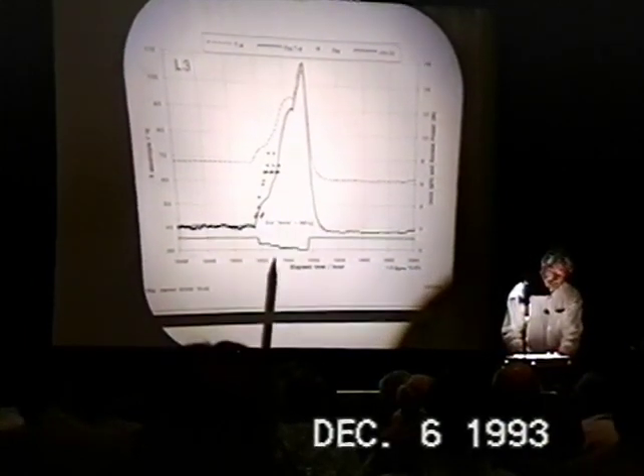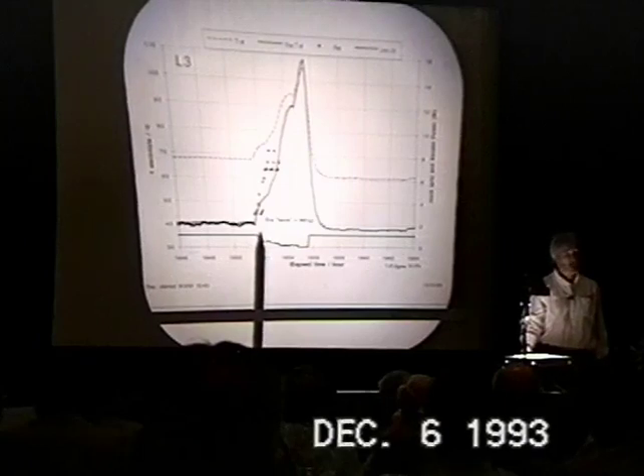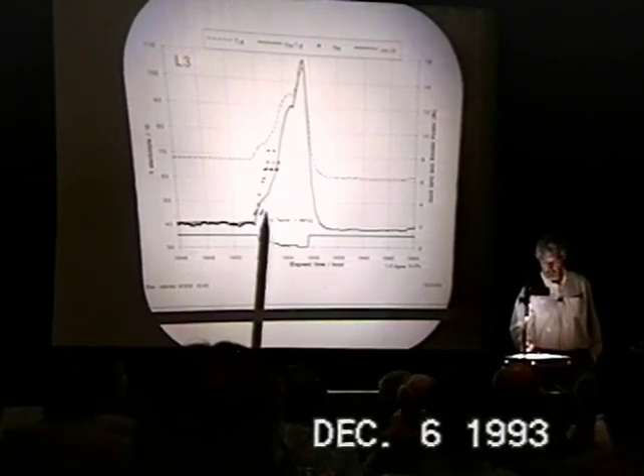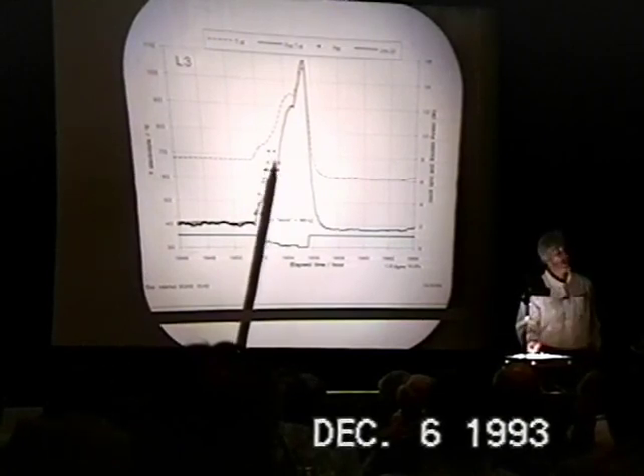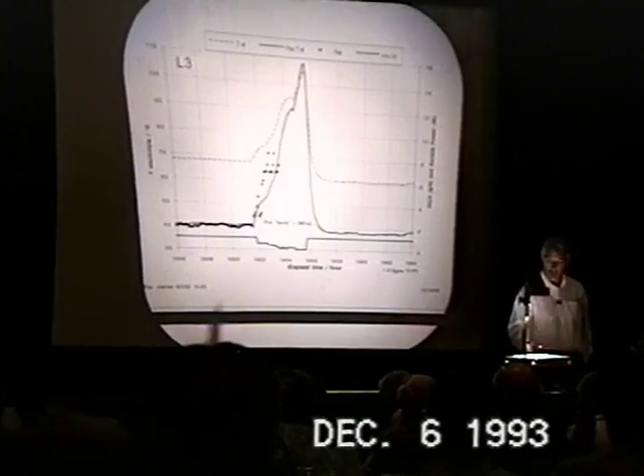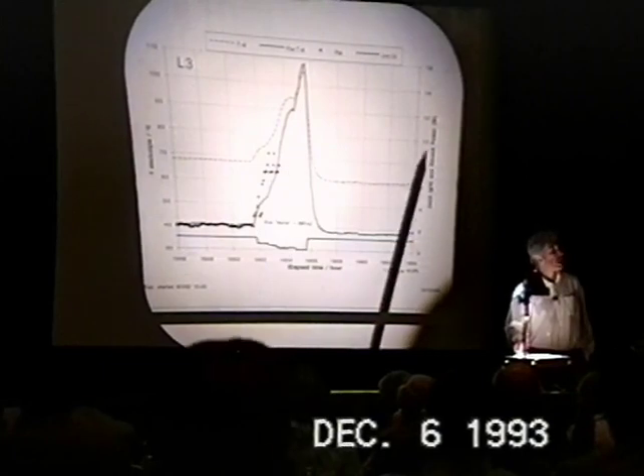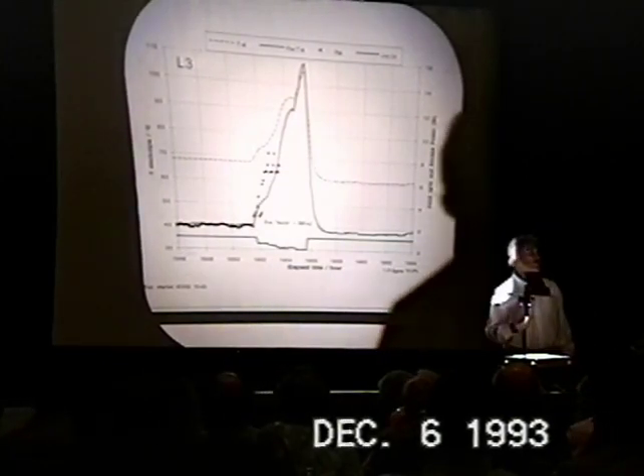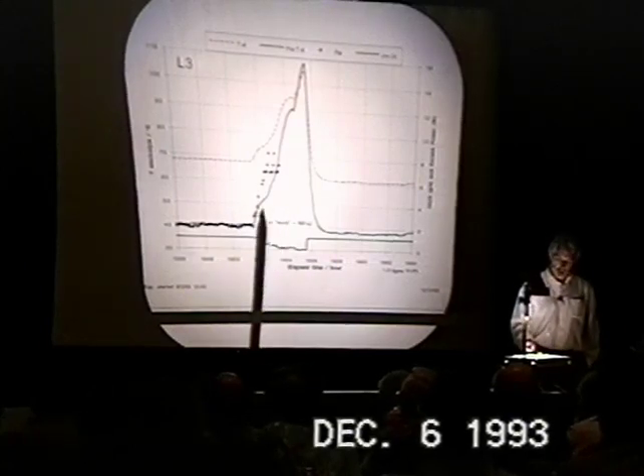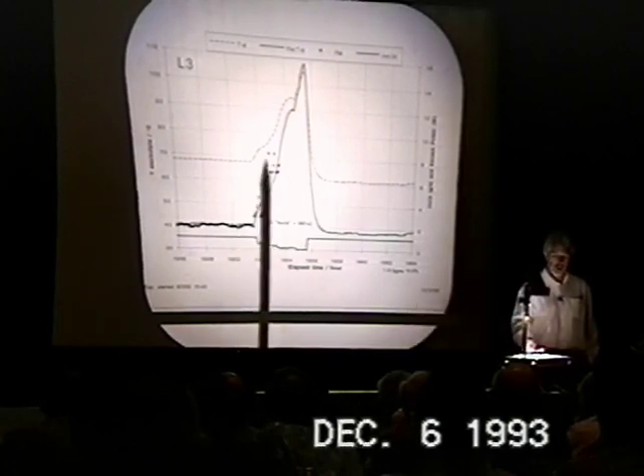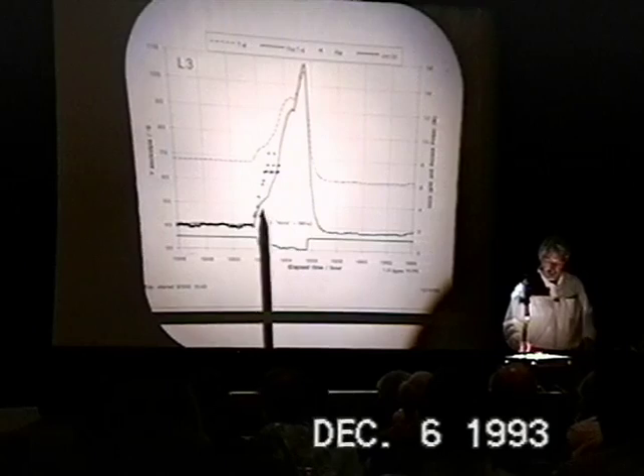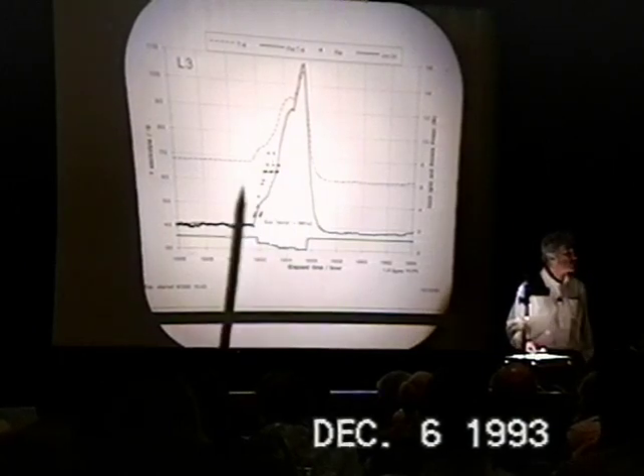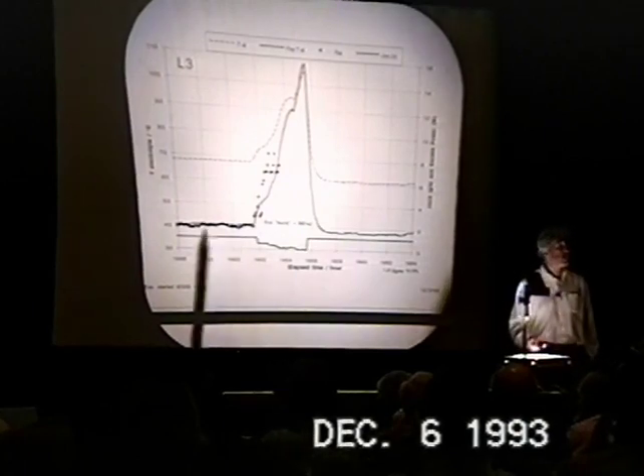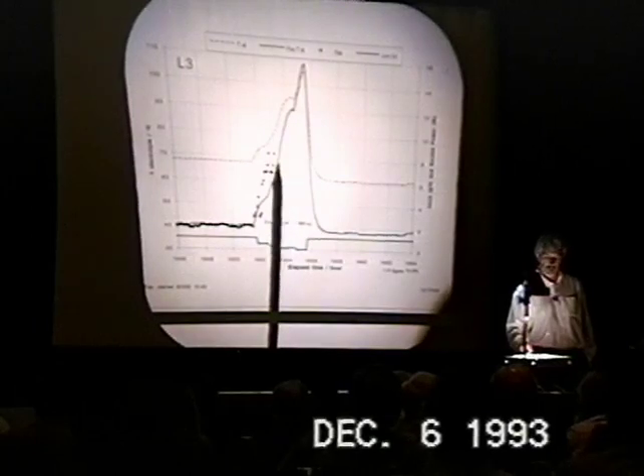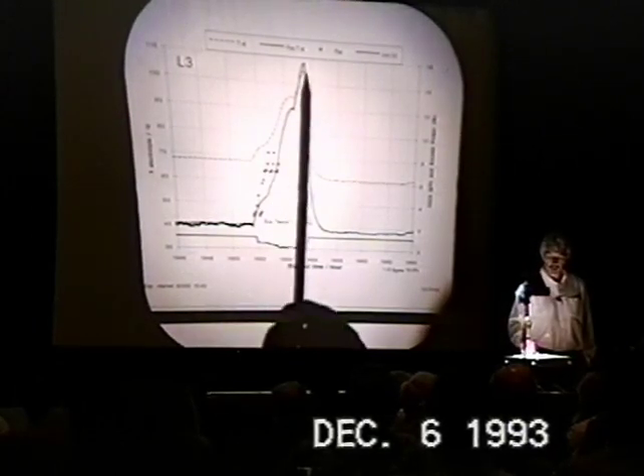So when we scrutinize this region, this is the point at which the mass flow rate blockage occurred. The magenta points are the excess power calculated by the conventional mass flow calorimetric calculation, going up to values of about 8 watts of power excess. The green line is this kludged isoperibolic calculation of excess power based upon the electrolyte temperature sensor, the dashed purple line here. And this value parallels that. The excess power calculated by this means parallels that of the excess power calculated in the mass flow calorimeter, and then proceeds beyond the point at which the temperature sensors shut themselves off to a value of about 16 watts.